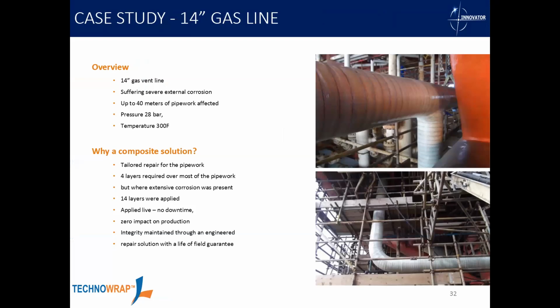Next slide. So this was a section of pipe that we repaired in the Middle East, and trying to keep the cost down for the client, we actually only started off by repairing the T-piece, but as we did more sandblasting, more defects were revealed, but they were much smaller defects. So what it meant was we could engineer the repairs for different locations of the pipe and different defects that we found. So in the T-piece, I believe we had 14 layers.